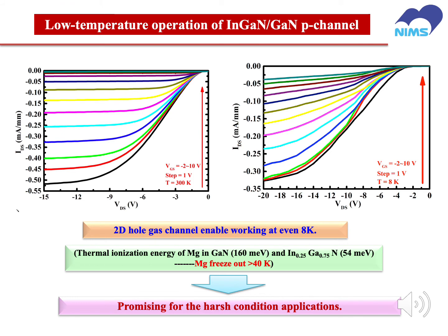So achieving the two-dimensional hole gas to fabricate the p-channel FET using the InGaN/GaN heterojunction is very promising, because this device can not only work at room temperature, but at extremely low temperature, like 8 Kelvin, the device also works very well. This is because the benefit of using the two-dimensional hole gas is that it is not dependent on temperature. It is quite different from dopant doping, for example using the magnesium dopant to achieve p-type, which has a thermal ionization energy and is quite dependent on temperature. At low temperatures, the magnesium will freeze out, but by using the two-dimensional hole gas to achieve the p-channel FET, the device does not freeze out, and this is very promising for harsh condition applications.